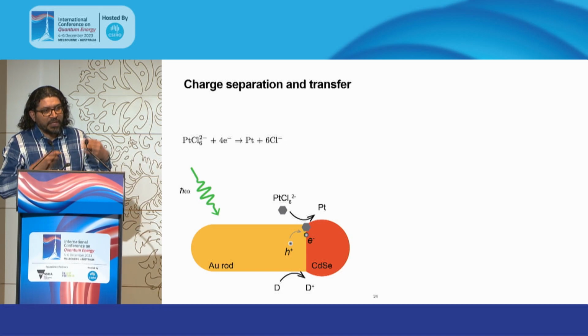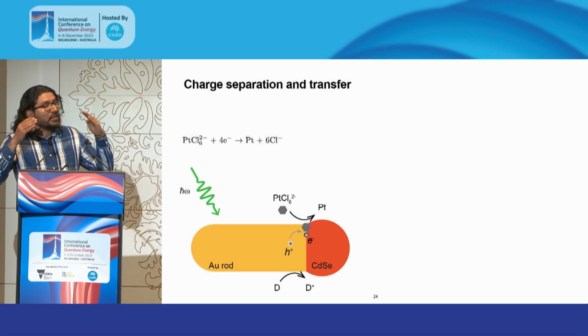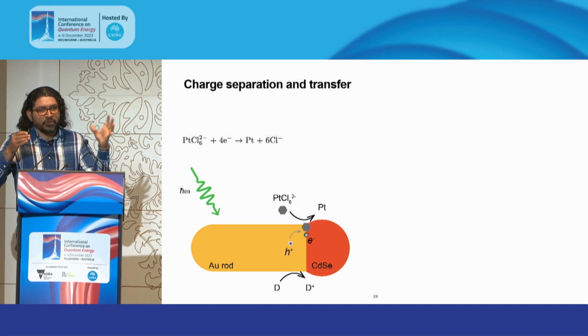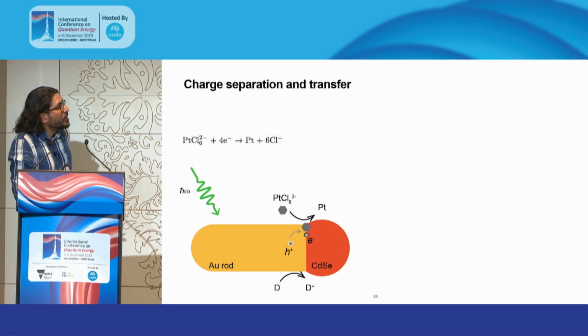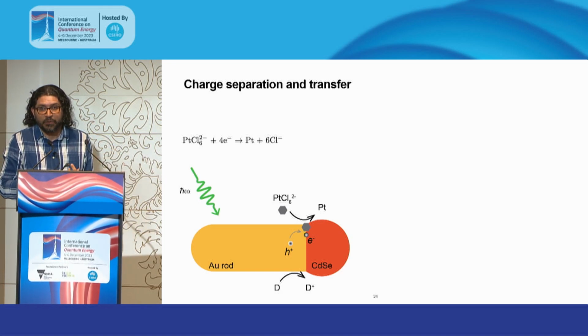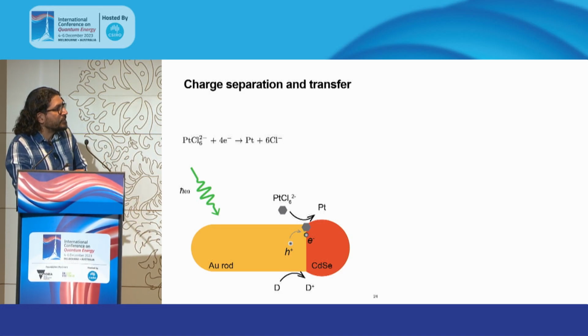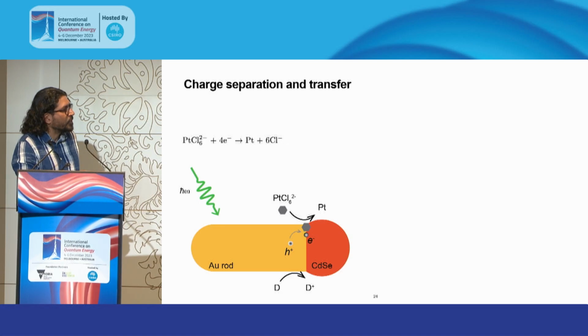So far, the electron microscope gives us insight into the line width. So what we measure could be the consequence of energy or charge transfer. So we did an experiment in the chemistry lab where we used this salt here that has platinum, mixed it with the particles, and illuminated the system. If there is electron transfer from the metal into the semiconductor, this electron could be taken up by the platinum salt, and platinum could deposit via a photoredox chemical reaction. If that were to happen, we would have platinum deposition here. And in the electron microscope, there is a very strong contrast between platinum, gold, and cadmium selenide.